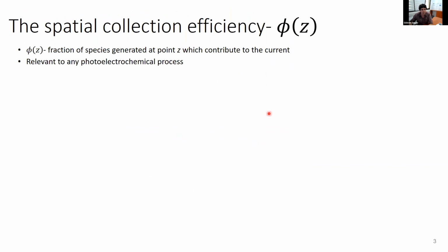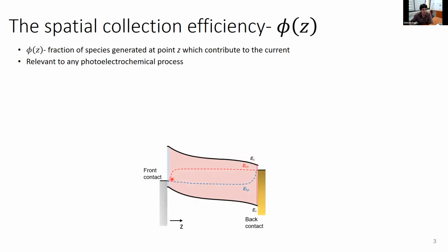And the idea is this: we use this term that we call the spatial collection efficiency, which is the fraction of carriers that are generated at a specific point that contribute to the current that you measure. For example, if we take this kind of solar cell, say p-n+ made from a lossy material, we can perhaps say that if carriers are generated near the p-n junction, there's a chance for them to be separated and collected by the contacts. On the other hand, if minority carriers are generated further away, there's a higher chance that they'll recombine somewhere.